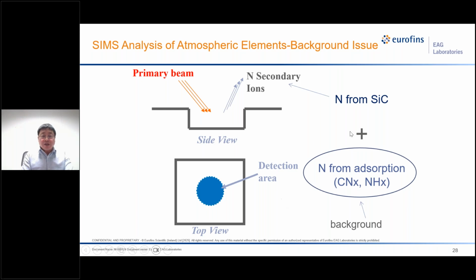So here it shows the process of the background. As the primary beam sputters the sample to create the crater, whenever the primary beam hits the center of the crater bottom, the signal is collected. The signal has two components. One is the nitrogen from the real sample. Another one is the nitrogen from the adsorbed species, that is CN and NH.